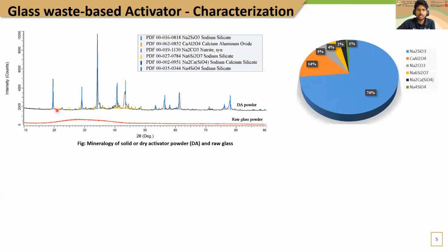However, the soda lime type bottle glass used in this study contains impurities other than silica. Therefore, the solid or dry activator produces other silicate and carbonate products with the heat treatment. So the efficiency of producing crystalline sodium silicate in the solid activator needs to be assessed. Using X-ray diffraction, or XRD, we could identify the mineralogy and then quantify the efficiency of producing crystalline sodium silicate. XRD results show that it produces more than 70% of sodium silicate.